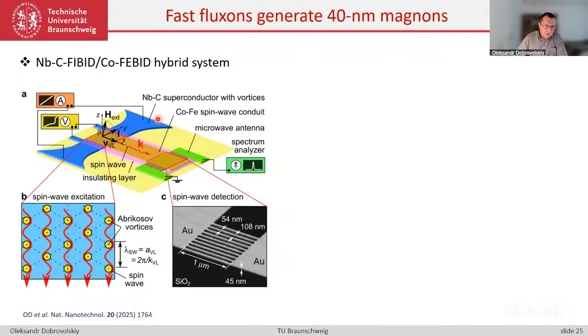In blue, you see the niobium carbide superconductor to which DC current is applied experimentally. In rose color, this is an insulating layer. So the superconductor was covered with a buffer insulating layer to avoid the proximity effect, so that vortices would be coupled only inductively, electromagnetically, if you like, with spin waves in the orange conductor on top. And then spin waves, if they are generated, propagate from left to right to the area where there is a microwave ladder antenna connected to a spectrum analyzer, and the spectrum analyzer is then used to monitor any high frequency signal which is associated with the propagating spin waves.